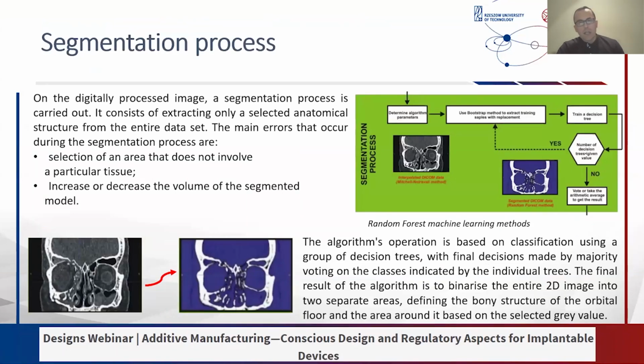Then we choose the segmentation process. When we started to cooperate with the surgeon, we used the traditional thresholding method. Also, we used a local thresholding method to increase the accuracy of the representation. But when we chose the interpolation process, we thought that we may choose a more accurate segmentation process for this area. So we choose not the thresholding method, but the random forest machine learning method. This method classifies using a group of decision trees, and this process